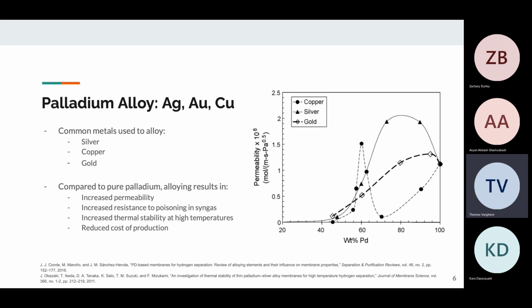As seen in the figure, the weight percentage used for alloying results in varying hydrogen permeability. To maximize permeance in palladium membranes, silver alloy weight percentage should be in the range of 10 to 30%, copper alloy weight percentage around 40, and gold alloy weight percentage in the range of 5 to 20%.